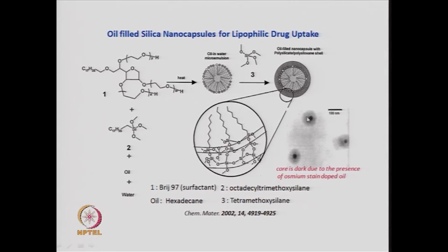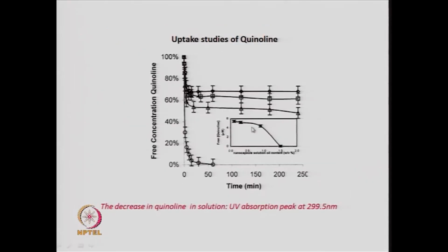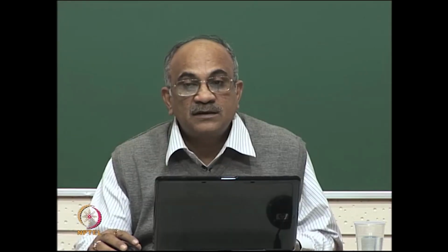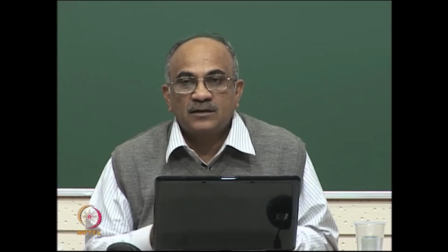So, the drug gets encapsulated within that core. You can study as a function of time this uptake of quinoline, which is given by the decrease in the intensity of the UV absorption at 299.5 nanometers for quinoline.